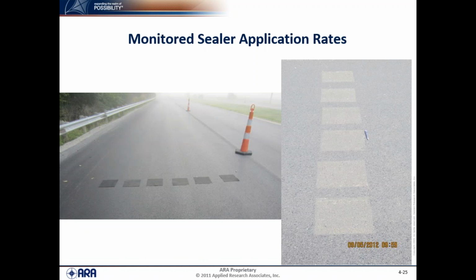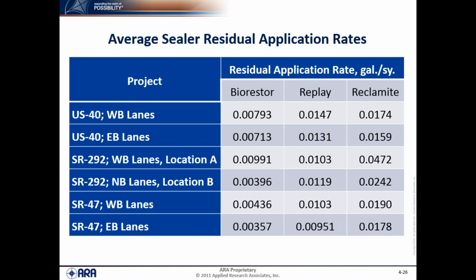Okay, the other thing is we monitored the sealer application rates. We put out these 1-foot square pads as shown here, and then removed them after the sealers and measured the residual rate of the sealers, calculated the average application rate of each one. Okay. This now shows what the average sealer application rates were for each of the suppliers. Also, I should say that the application rates were defined by the suppliers themselves. During the project, that was already predetermined on what they would apply, and the project really didn't specify what rates were to be applied. That was left to the sealers themselves.